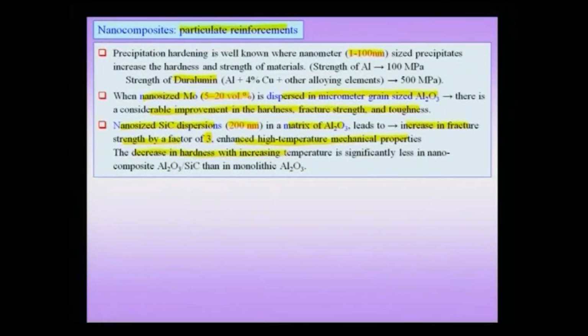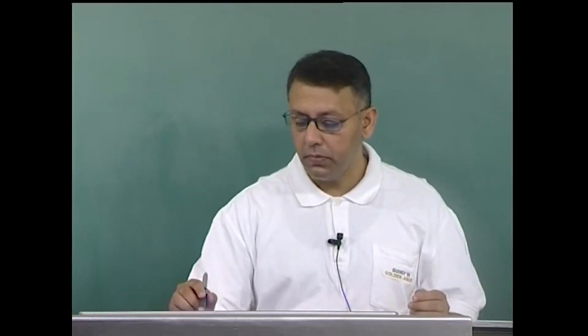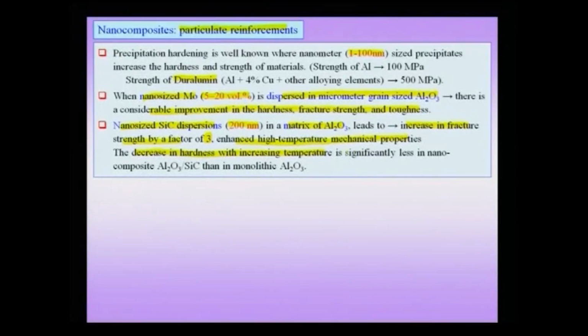There is a decrease in hardness with increasing temperature, which is what you expect, because now you can have thermally activated motion of dislocations. In other words, in normal alumina at room temperature, the strength is very high because dislocations are not that glissile, the Peierls stress is very large. But then when you go to high temperature, some of these will start showing plasticity, because now you can have thermally activated slip, and also other mechanisms like grain boundary sliding may start to take place, and therefore, this softening effect is significantly reduced when you use an alumina silicon carbide composite rather than a monolithic alumina.